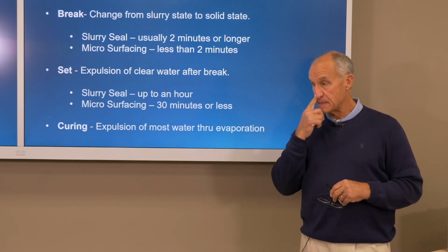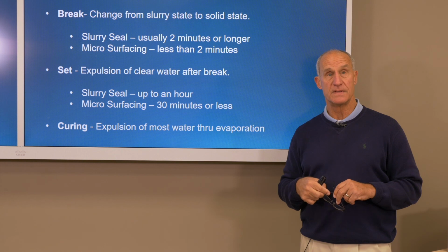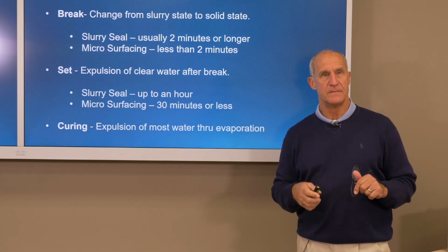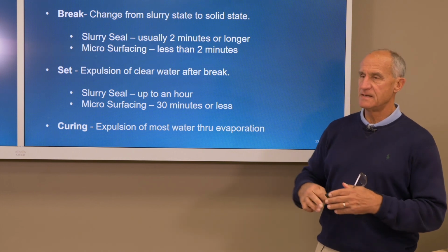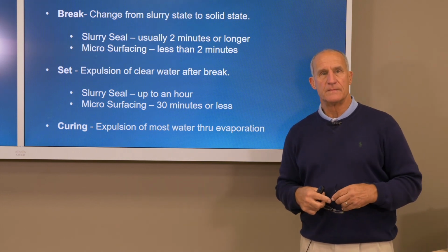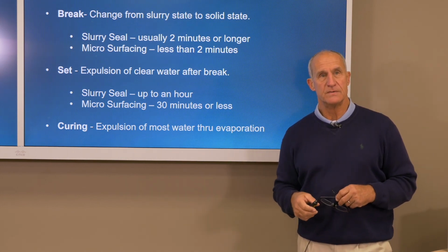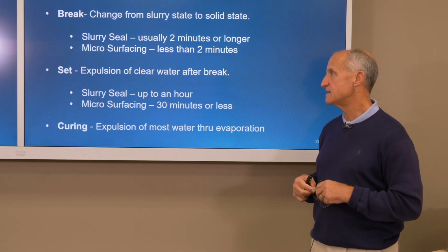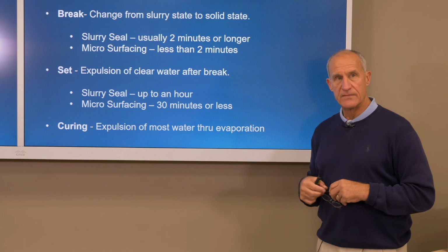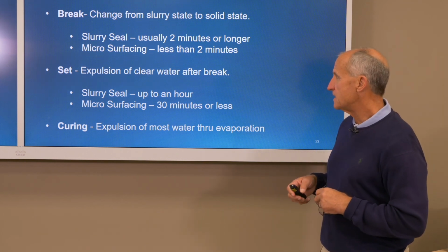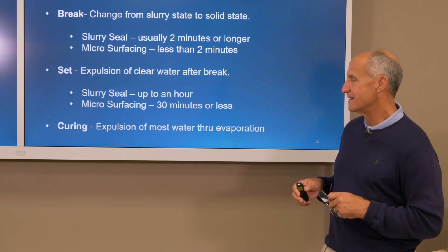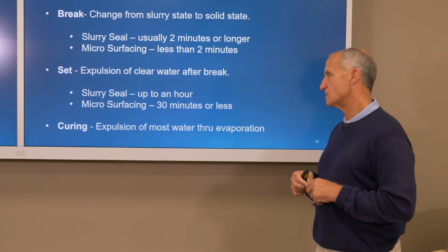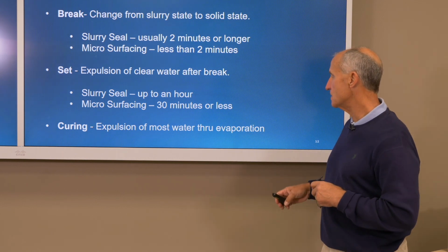Now, if you were to happen to take your boot and walk across that mat within that 30 minutes for microsurfacing, or within an hour with Slurry Seal, you may see some clear water being pushed out from the edge of your shoe. That's when the material is beginning to break, or rather to set. It's not quite ready for full-time traffic just yet, but it's well on its way, and that's an indicator that you probably have a mixture that's on track to doing just what it's supposed to do.